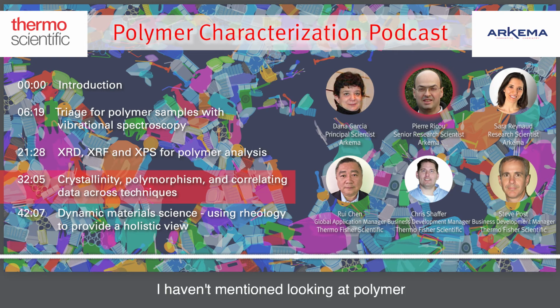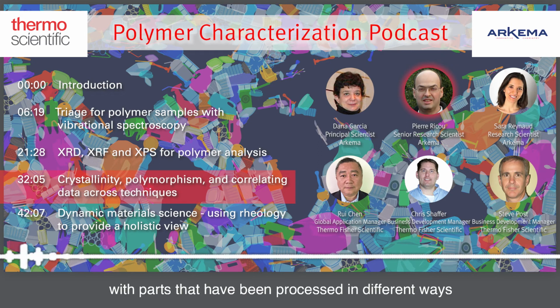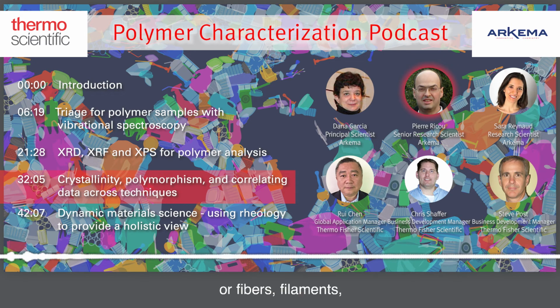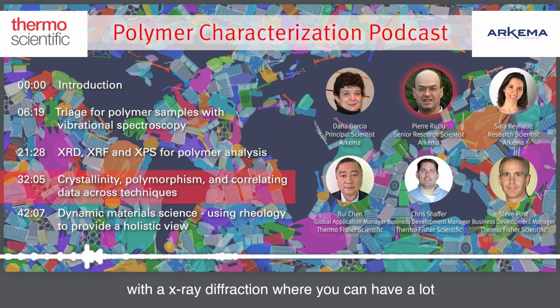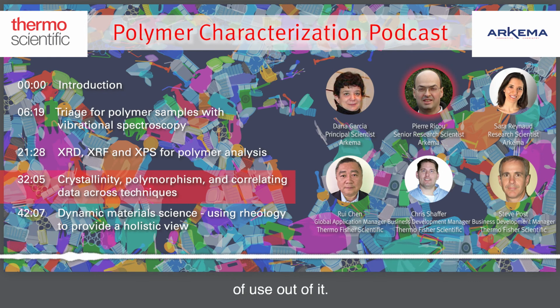I haven't mentioned looking at polymer orientation as well, but if you're dealing with parts that have been processed in different ways, or fibers, filaments, and you want to get some idea about orientation, it's definitely possible to do with a 0D or 1D detector. It's just a little easier to also do that with a 2D detector, because now you get a full picture, if I may say, of those Debye rings, so you can quickly assess if you have presence of orientation. So kind of in a nutshell, focusing more on the polymer field, X-ray diffraction is where you can have a lot of use out of it.